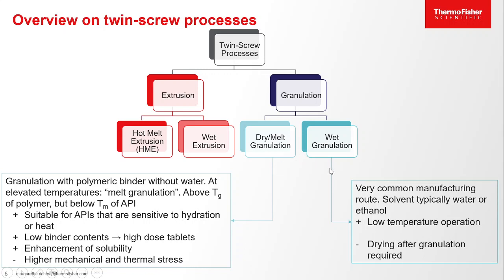Then higher mechanical and thermal stresses can occur, of course, so this is a downside of the process. Wet granulation, on the other hand, is a very common manufacturing route. Typically, different techniques are used, but all of them have in common that there's a solvent, typically water or ethanol, added into the process. If we perform this with a twin-screw process, then this granulation process is continuous, and this is the big advantage here for continuous manufacturing. The process itself is performed at low temperatures, so this is a big advantage, but because you add a liquid, you have to dry the liquid afterwards, and you have the solvent handling that needs to be taken care of as well.